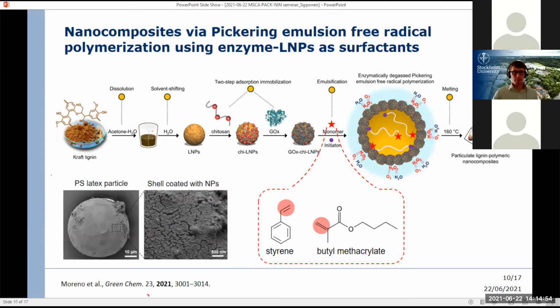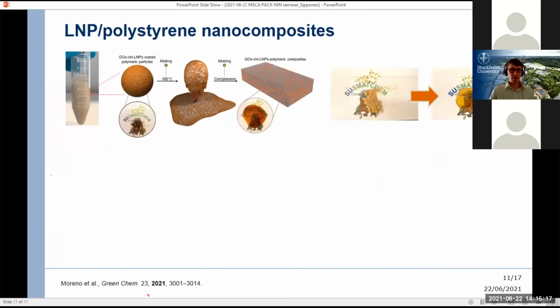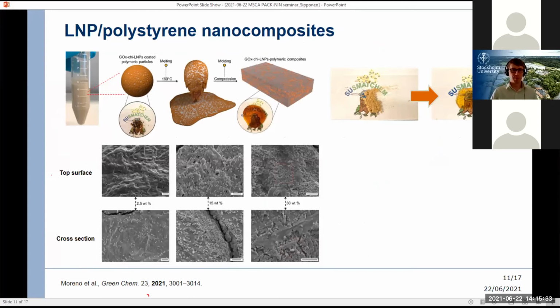And what we found is that, well, this is the SEM photo of the emulsion particle that has been polymerized. So this latex particle, which is coated by the nanoparticles on the shell, formed basically very nice material that could be used for the melt processing. So forming these composite films and specimens was really straightforward. We just simply dry the emulsion and then melt cast it into composite shapes.